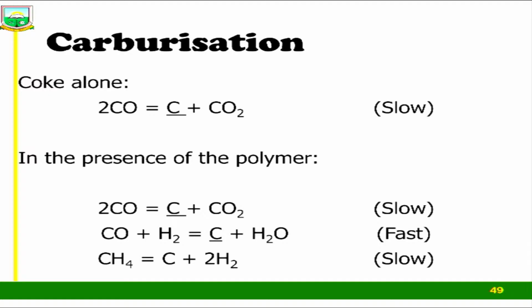Every iron must pick some carbon so that when you are melting, you can cut down on the temperature, because it's also a way to reduce your energy. We did some carburization, and we saw that when you use only coke, the conventional material, the carburization was slow, but in the presence of the polymer, you had hydrogen reacting to give a very fast reaction. For this reason, carburization was also better for the polymers.